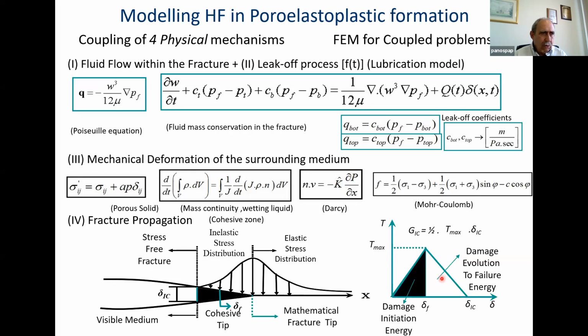And just to say for people who do such modeling, the shape of the softening of this curve is not very important, whether it is linear or exponential. What is important is the area under the curve, which is equal to the strain energy release rate. We found also that the initial slope, the stiffness, will be important in hydraulic fracture.